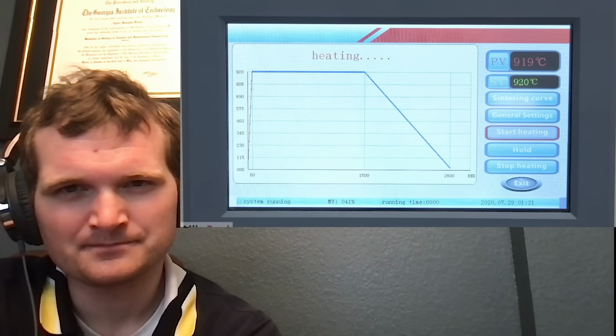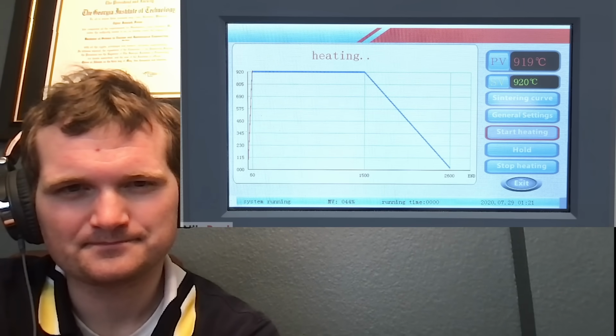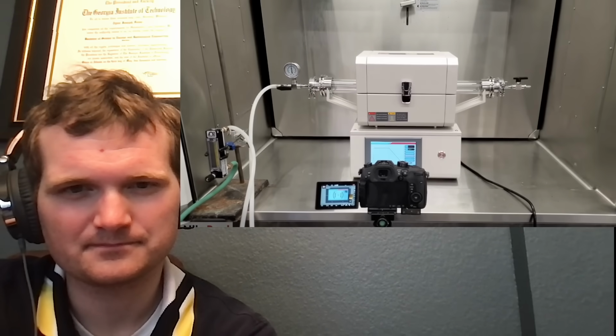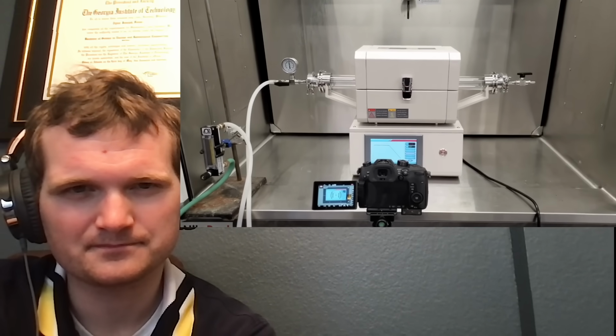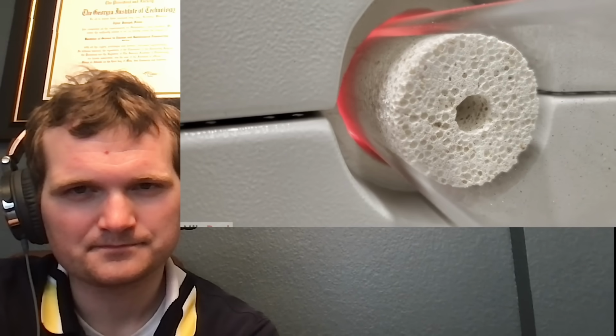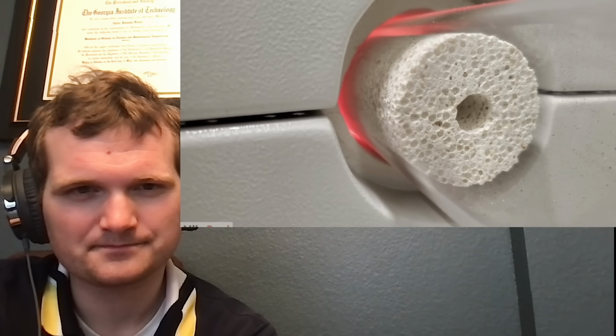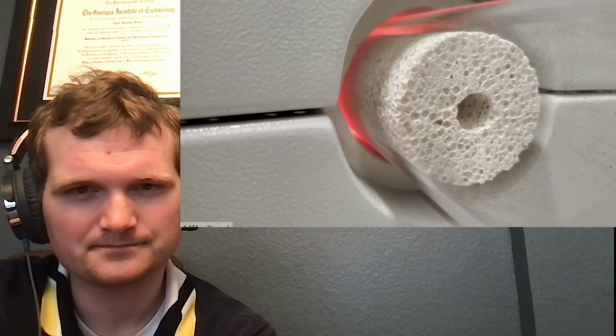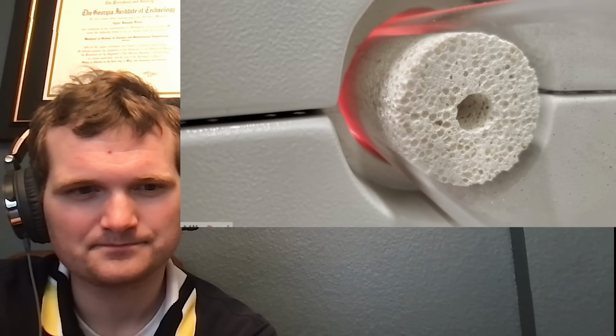At this point, it was at the max temperature of 920C, and on the outside, it didn't look like much was going on. If I looked in from the side, though, I could see that it was glowing red. It was going to have to cook like this for another 9 hours, and then it would be slowly cooled over 18, and I just left it overnight.